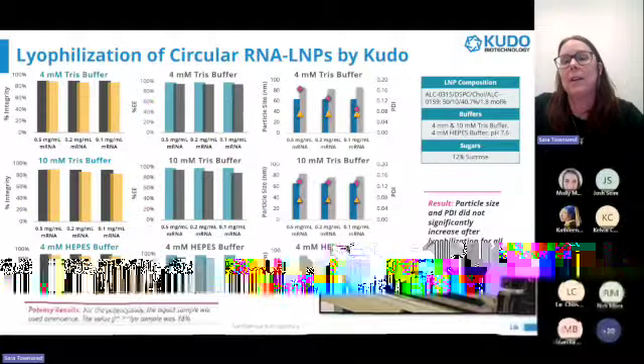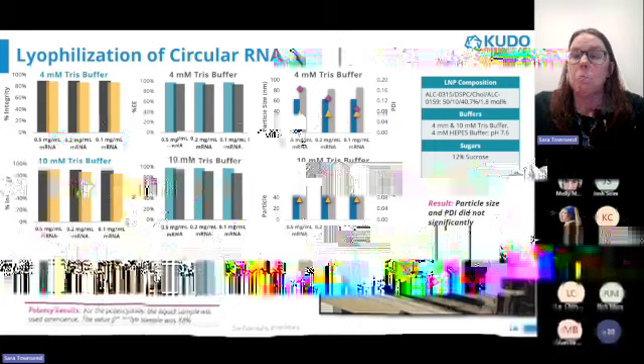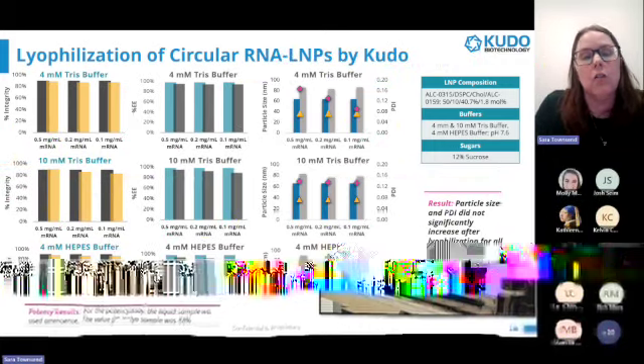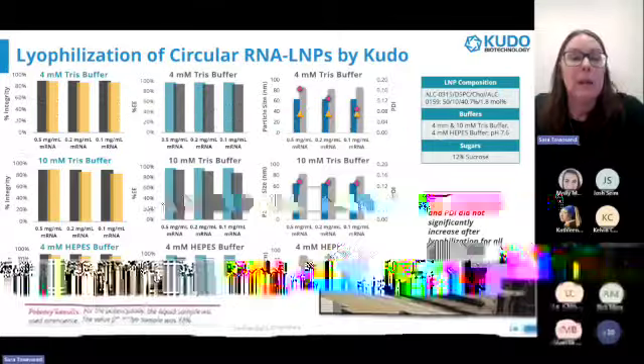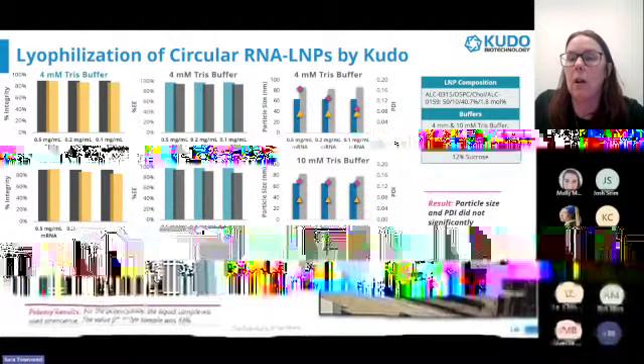Following the success of our mRNA-LNP lyophilization, Kudo took it one step further to lyophilize circular mRNA-LNPs. Again, all three conditions worked very well, and there was only minimal size growth. Note that in addition to Tris, Kudo investigated HEPES buffer, which had not been explored by others. Kudo also tried each formulation at three different concentrations and did not see a significant difference, which is very useful data.